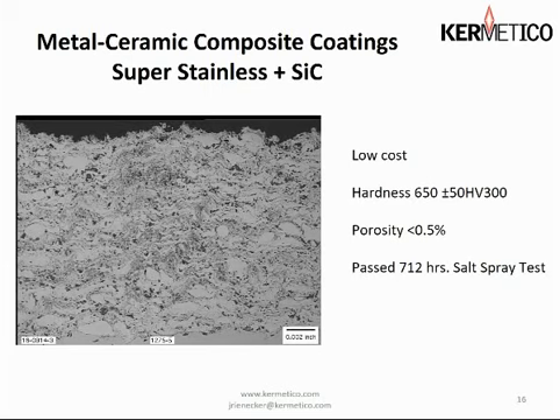And we find that this makes for a much better coating. Interestingly enough, you would think that it would interfere with the machinability of the coating, but it does not. So we're literally spraying metal matrix composites. Makes for very good coatings. This one has less than 0.5% porosity, and it passed through a 712-hour salt spray test.